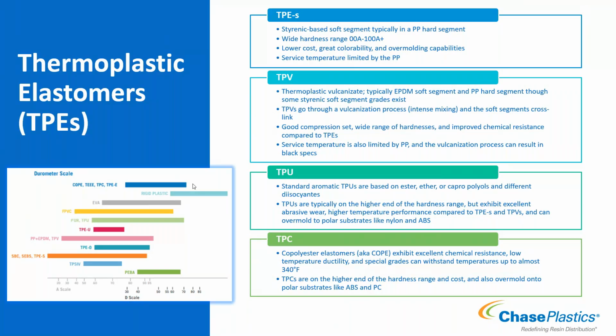TPVs - that stands for thermoplastic vulcanizate. It goes through an intense mixing process, the vulcanization process, that forces the soft segments to cross-link. Because of that cross-linking, it acts a little more rubber-like, so you get a bit better compression set performance and a bit better tear strength than you would out of a standard styrenic-based TPE that's not been cross-linked. Most of the time, TPV grades are going to be EPDM with a propylene hard segment, though there are some styrenic soft segment grades that exist - they would vulcanize the styrenic rubber instead of EPDM.